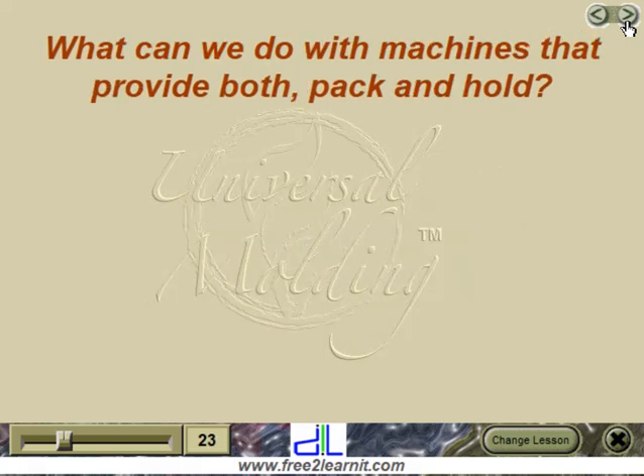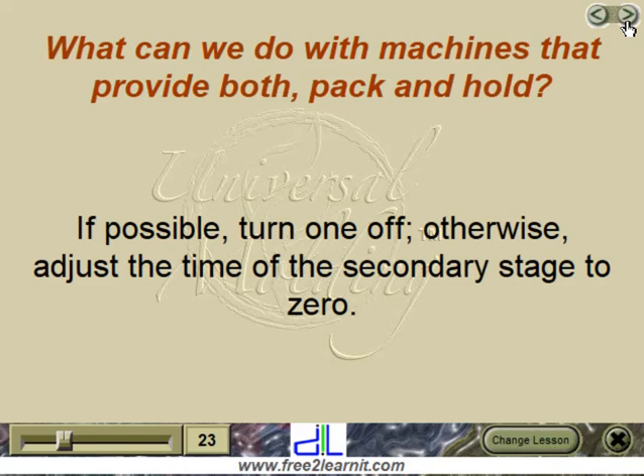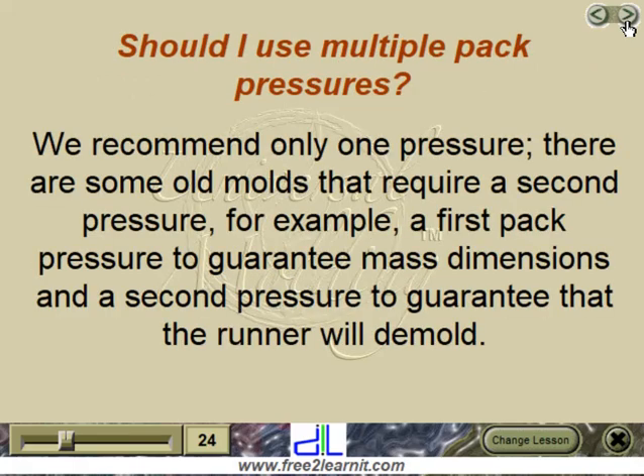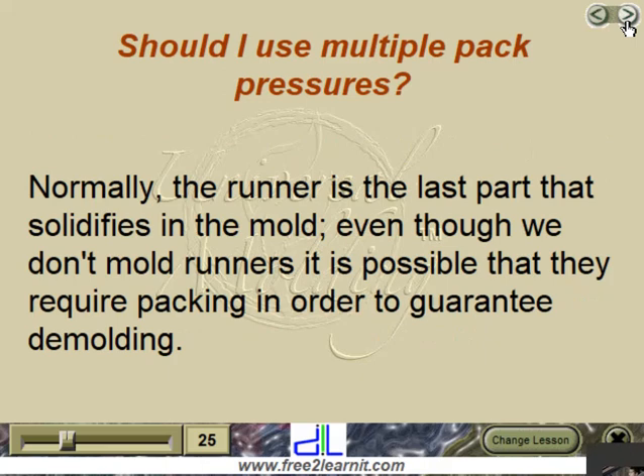For machines that provide both pack and hold, if possible turn one off; otherwise adjust the time of the secondary stage to zero. We recommend using only one pack pressure. There are some old molds that require a second pressure — for example, a first pack pressure to guarantee mass dimensions and a second pressure to guarantee that the runner will demold. Normally the runner is the last part that solidifies in the mold, and it may require packing to guarantee demolding.